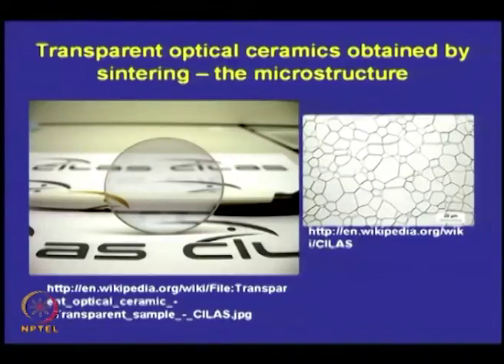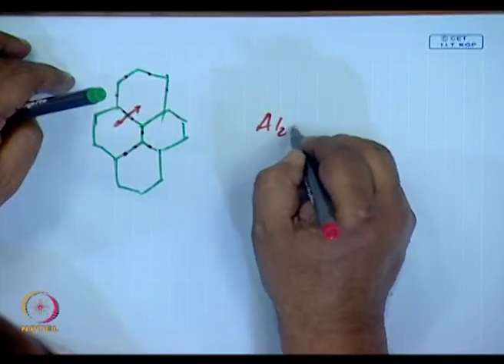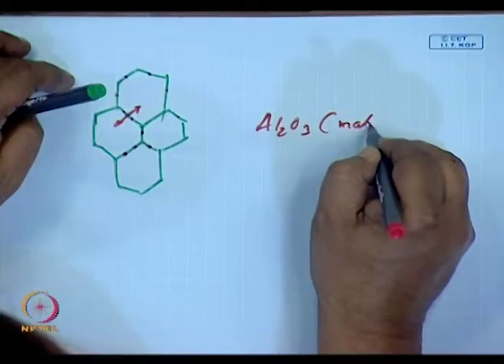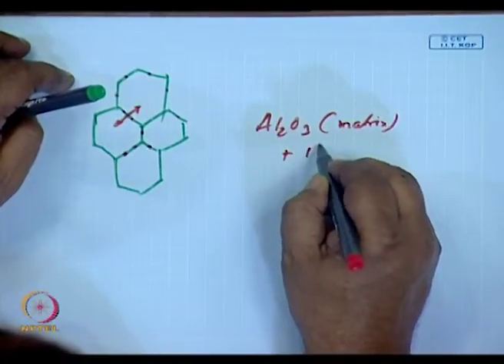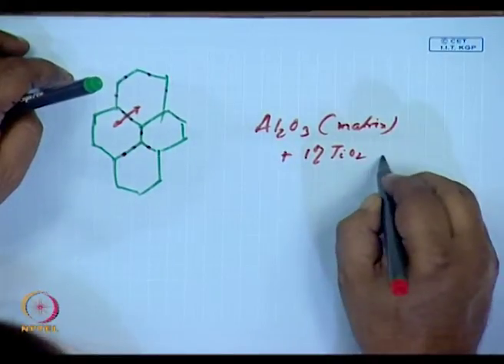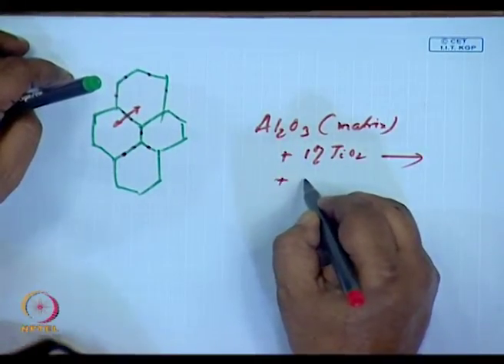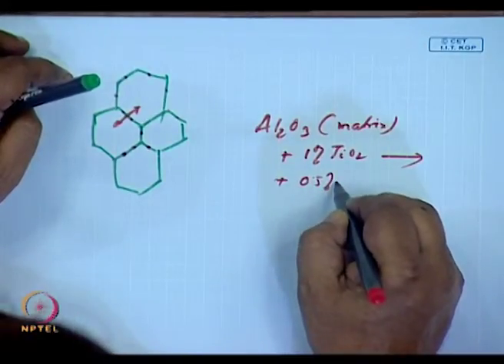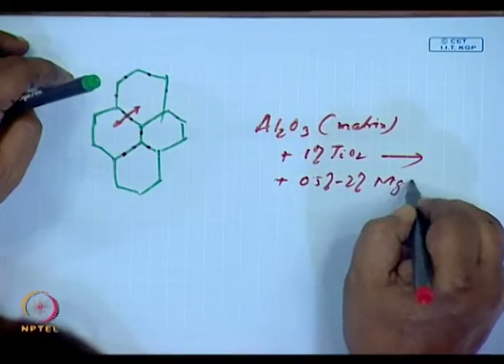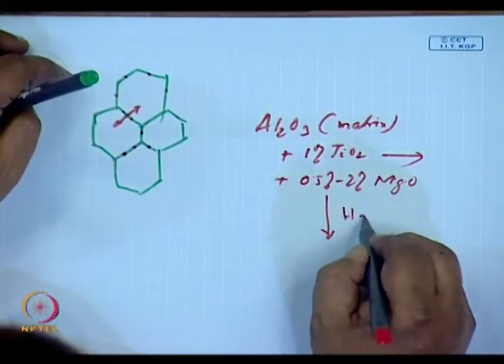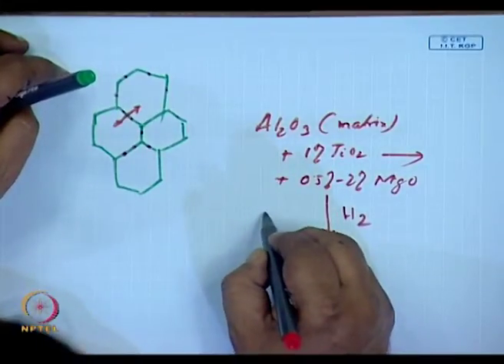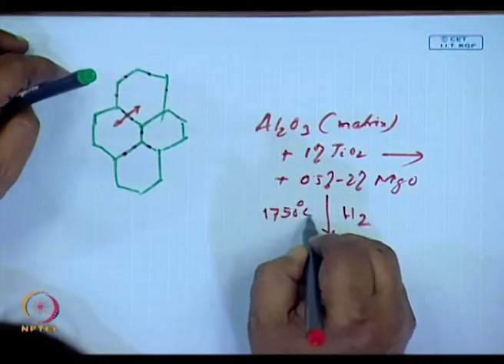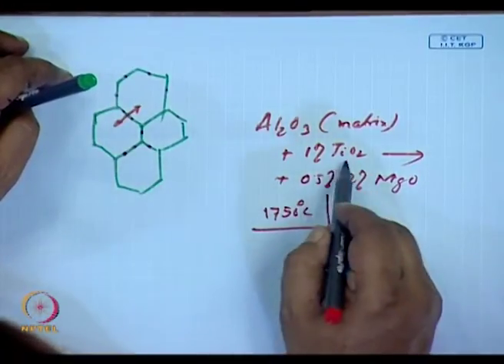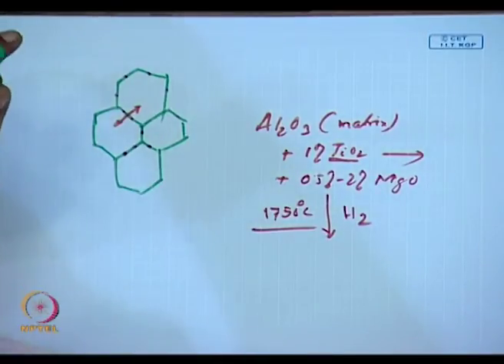These sodium vapor lamps are made by taking alumina as matrix plus 1% titanium dioxide, which is the sintering aid, plus 0.5% to 2% magnesium oxide depending, and firing it under hydrogen gas at anywhere from 1750 degrees centigrade or higher. What the titanium dioxide does as a sintering aid is abstract oxygen from the alumina matrix, creating defects so that diffusion does occur.